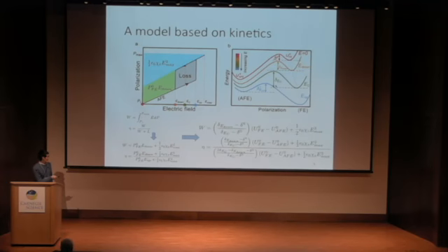And the second term is unchanged. In the first term, we have four different parameters. This delta E down is the effective kinetic barrier that happens at the transition. And delta 0 is the ferro to antiferro transition barrier at zero field. And this delta EC is the barrier height when the antiferro and ferro phases have the same energy. This energy difference, delta U, the UF E naught minus UAF E naught, is the energy difference between the two phases at zero field.